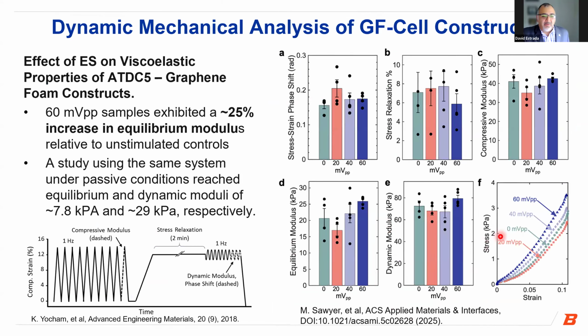And then we decided to apply electrical signals, 0, 20 millivolts, and 40 and 60 millivolt peak to peak during the cell culture. And so we did this for 5 minutes a day over 7 days and cultured out for another 7 days. So 14 days total of cell culture for ATDC5s, and looked at the dynamic mechanical response for the grown tissue, right? And what we noticed is that the 60 millivolt peak to peak samples showed a 25% increase in equilibrium modulus, right? So that's this plot here. It wasn't really significant when you look at the statistics, but it's still an increase.